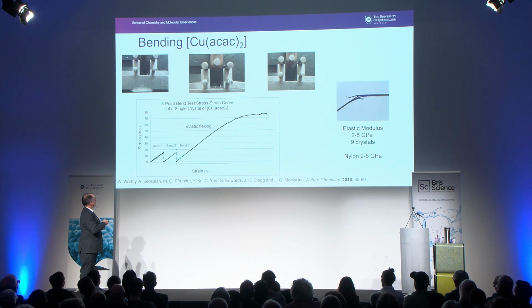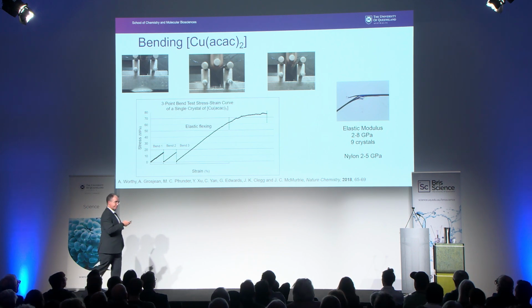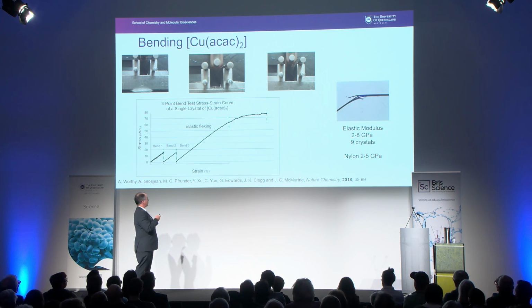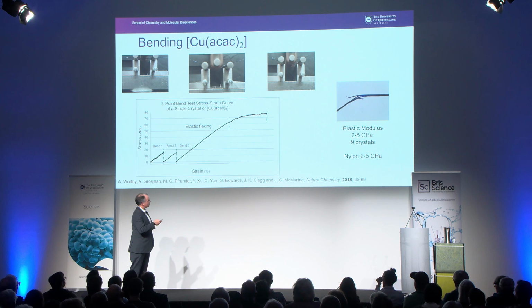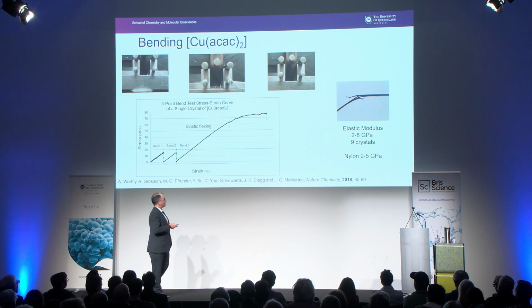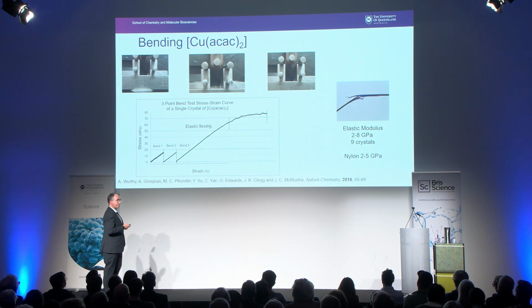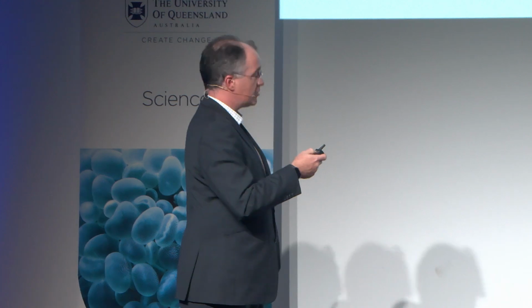And you can keep on bending it until you reach a point a bit over 1% strain where we start to see irreversible deformation, and it plastically deforms and it ends up looking like this. So there is an elastic limit at about 1% strain. The elastic modulus that we get out of this from 9 crystals ranges between 2 and 8 GPa, and that's about the same as nylon. So these crystals are behaving just like soft materials.